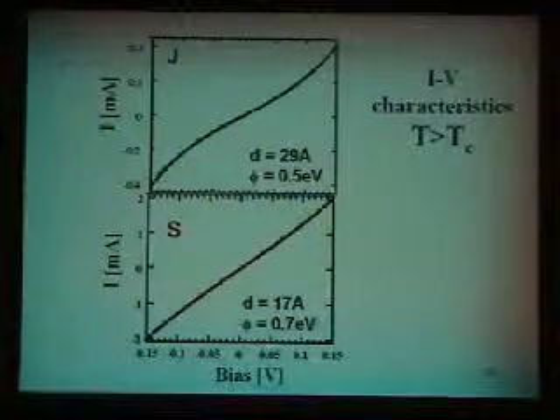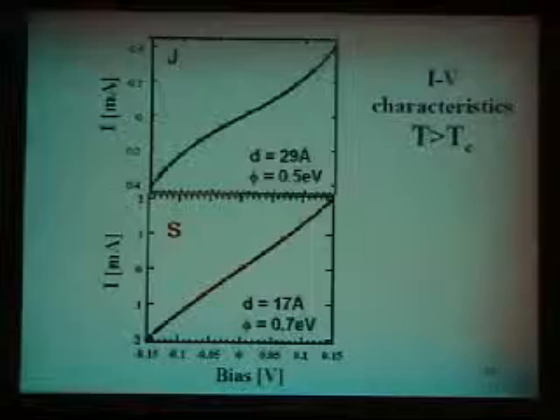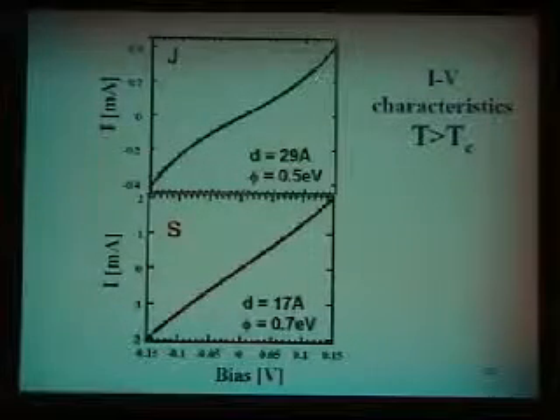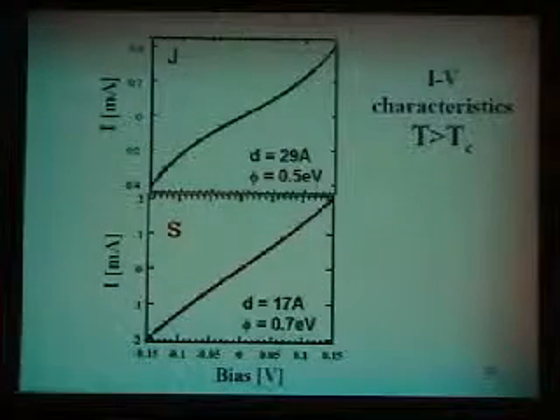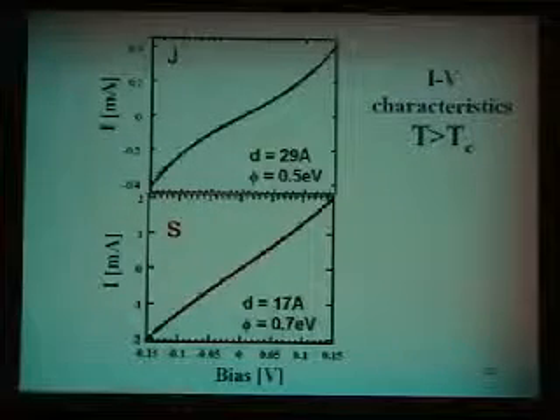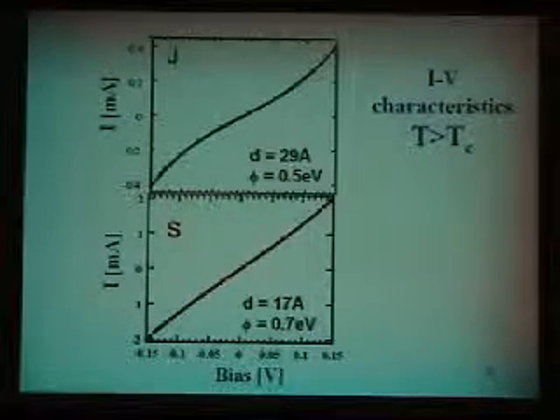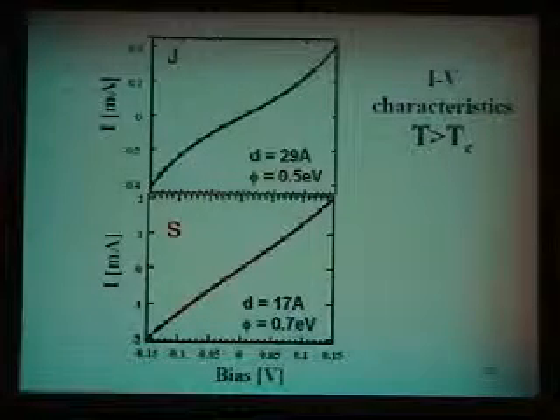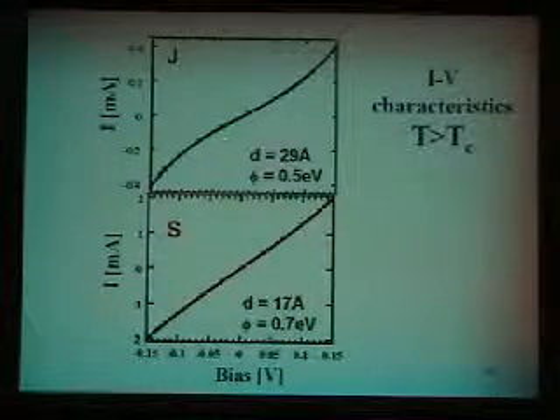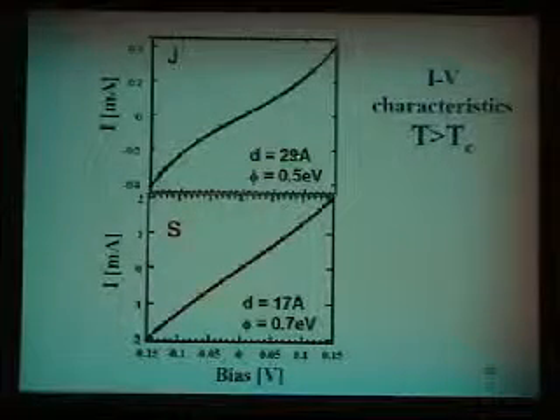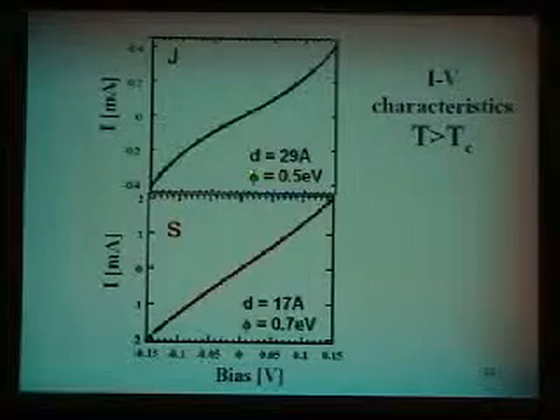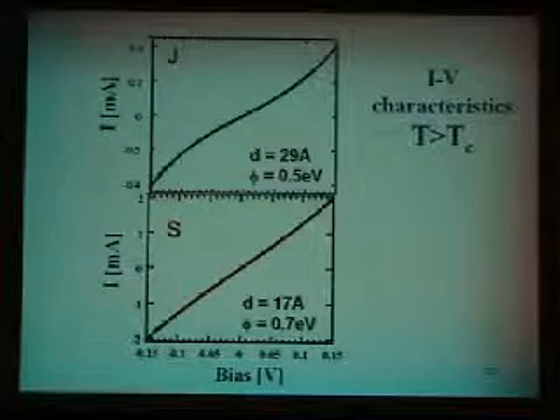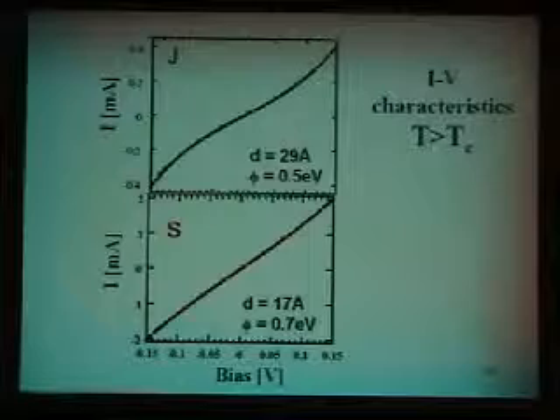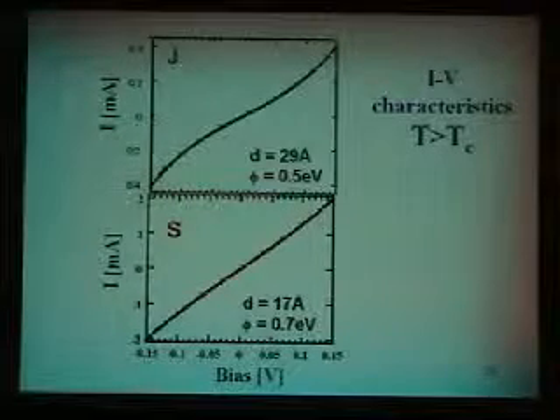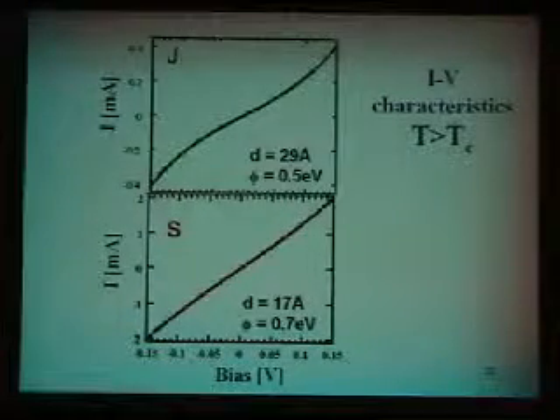So here it is, what I call the junction and what I call the short. There it is, the IV characteristic. This is what everybody does. You look at the IV characteristic and you fit it to either the Brinkman-Dynes-Rowell model or the Simmons model, one of the two. Notice the fit looks very good, and there are the parameters you get. The thickness of the barrier is 29 angstroms, this is above Tc, and the barrier height is about half an electron volt. They don't know anything else about this, so you figure, half an electron volt and some angstrom thickness, so that must be right.